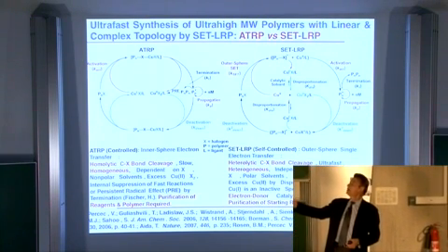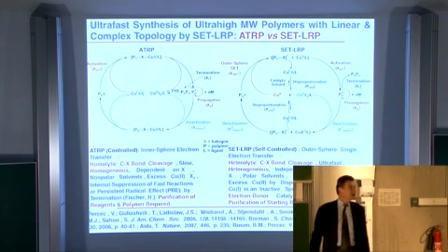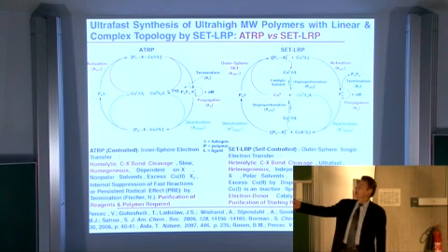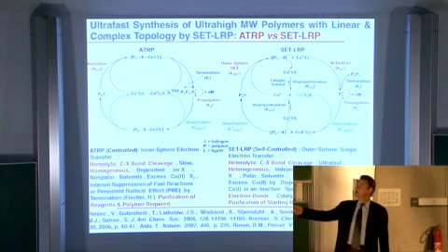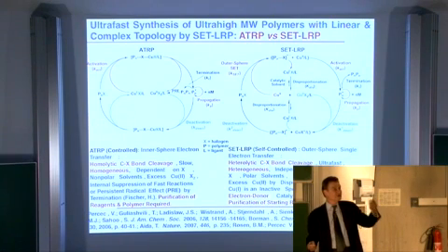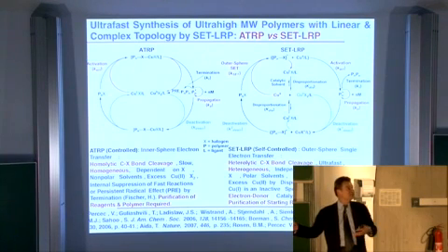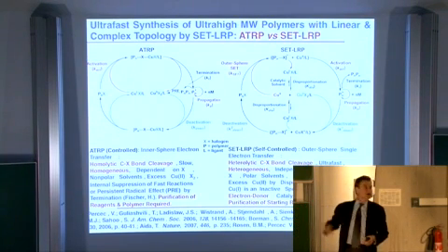You generate copper-1, and you don't want copper-1 because there is no mechanism to put the alkyl halide back on the radical. Therefore, what we have found is that a combination of solvents and ligands provides a disproportionation of the copper-1 generated in situ back into copper-0 and copper-2.